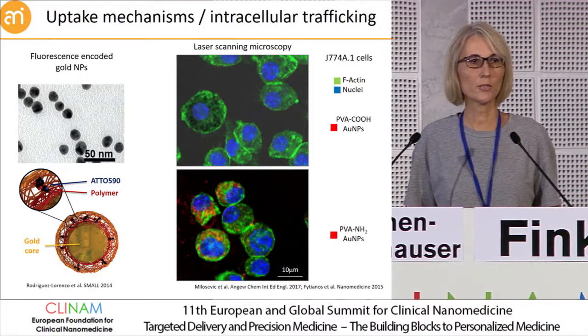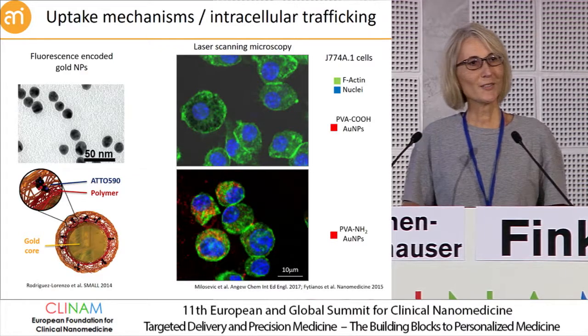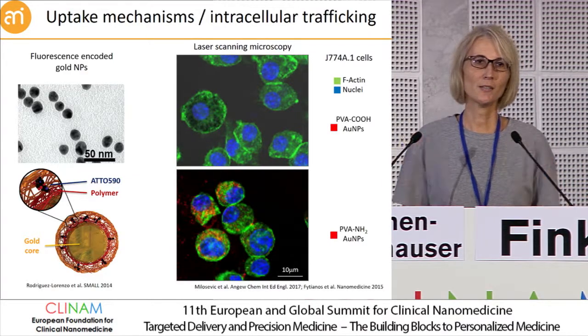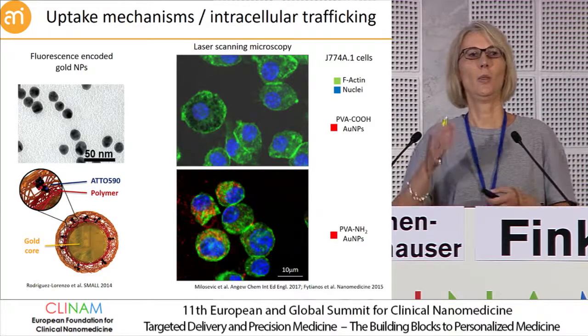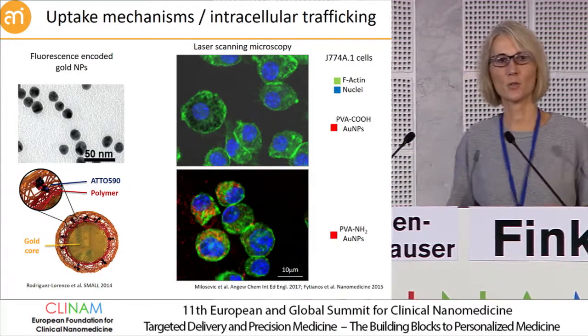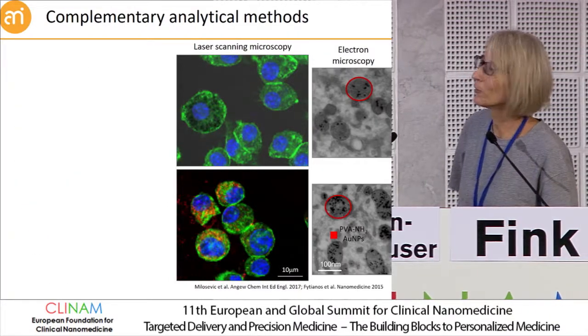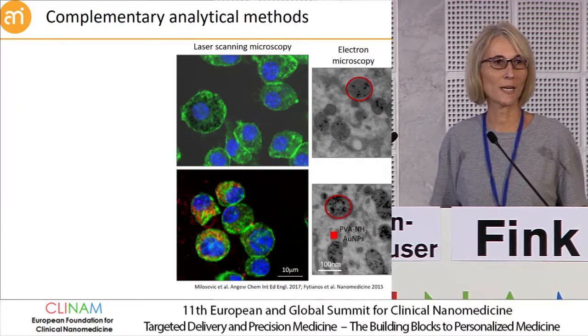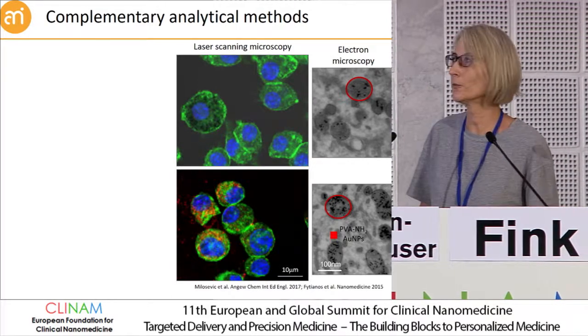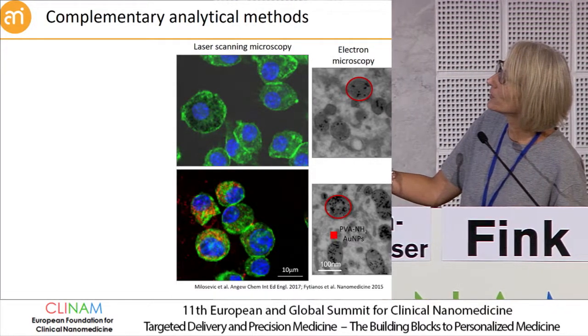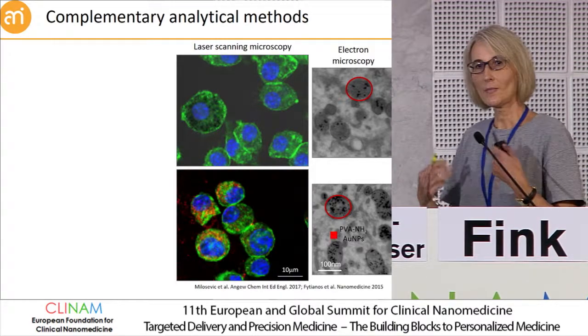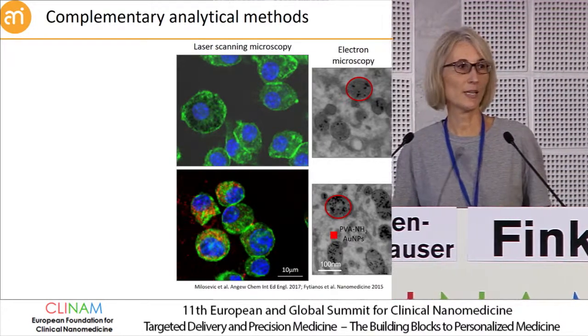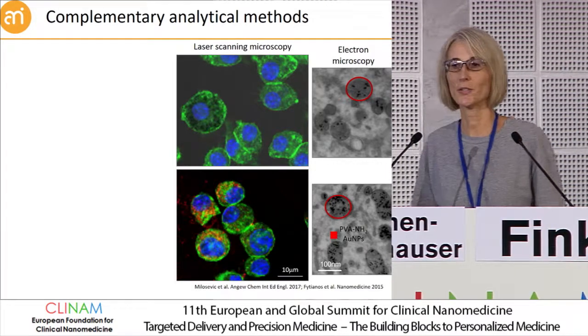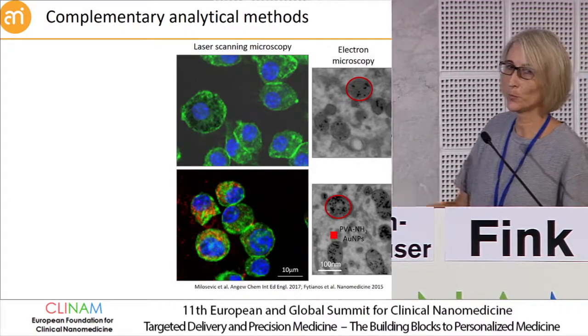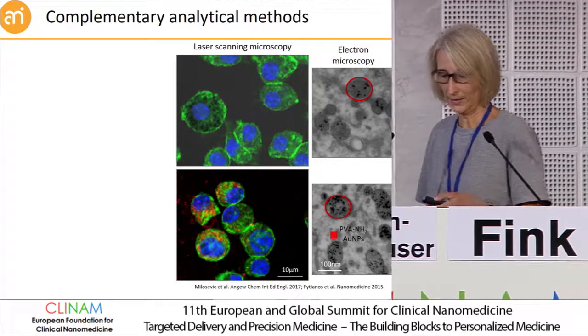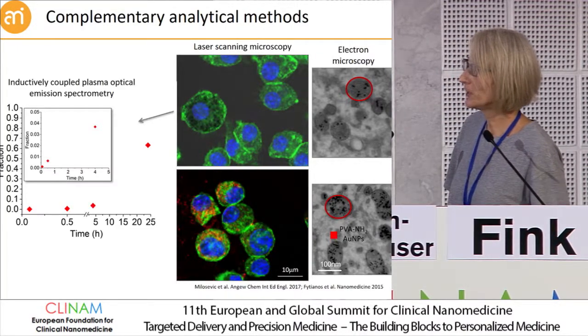So the first conclusion is negatively charged particles are not taken up by the cells because they have a negative surface charge of the membrane. No, this is not true. This concept does not work, because if we look with other methods, like transmission electron microscopy, where we can see the gold core of the particles, you also see that the negatively charged particles are inside the cells in the endolysosomal system, and they are quite numerous in comparison to the positively charged particles. So there is something different which we didn't know at this time.